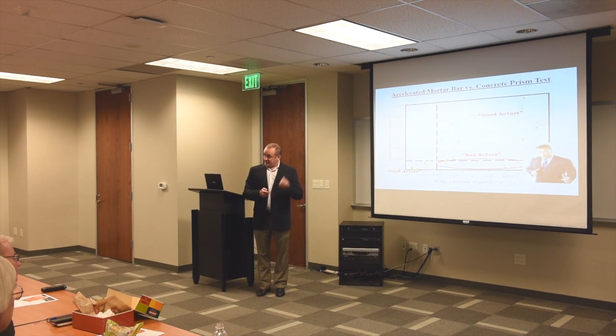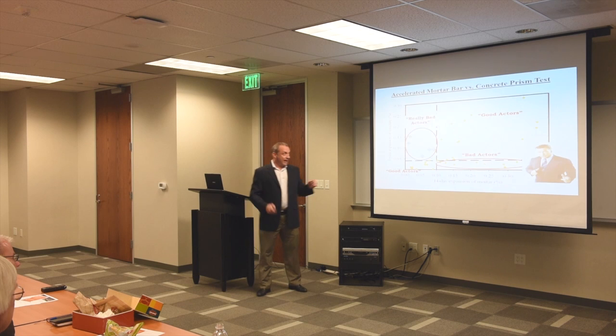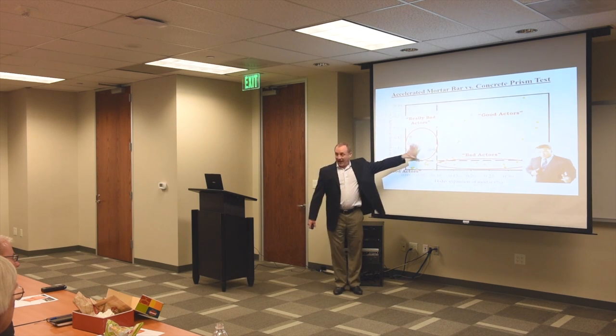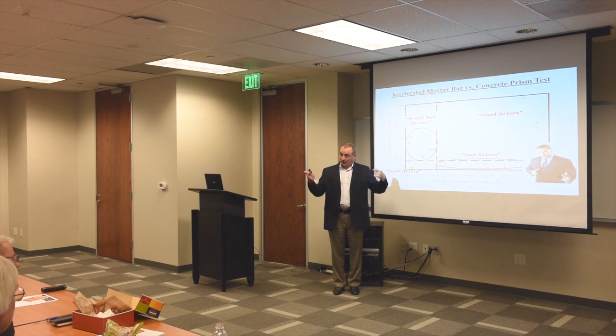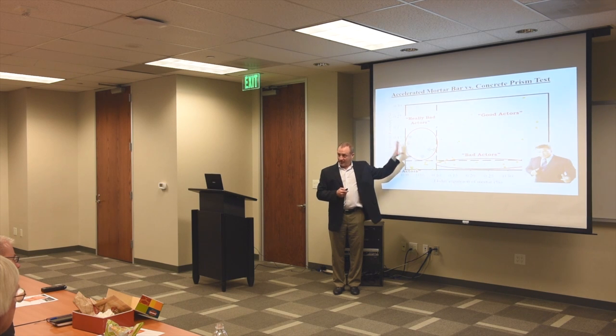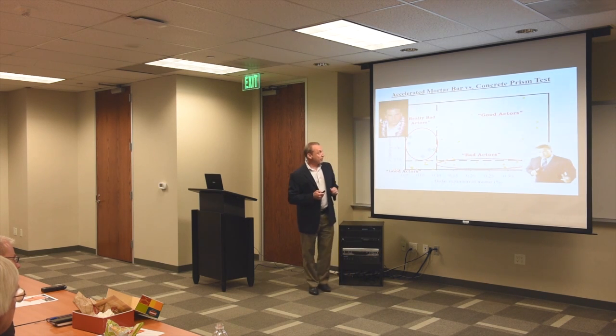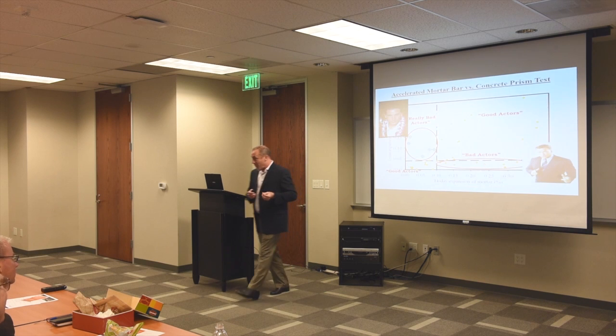What we didn't realize, and this is a big issue in Texas, is there are aggregates that actually pass this quick, accelerated and aggressive test. So you would think intuitively it's got to be good stuff if it passed that test. But in fact, a lot of these aggregates will fail in real concrete. These are what we now refer to as the really bad actors.